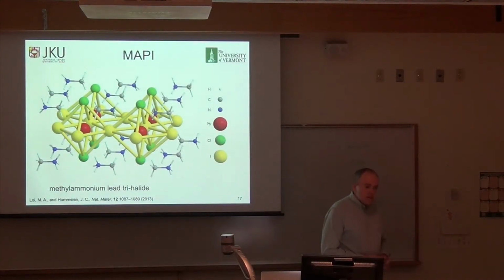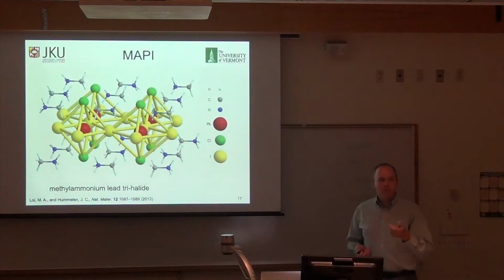To clarify what the material is — this is the material of incredible interest to everybody around the world right now. This is basically what Henry Snaith used, and the only one that works particularly well. This is MAPI, methyl ammonium lead trihalide, or triiodide. There's a lot of discussion: to make a very good film, you blend in a mixture of lead chloride and lead iodide, but nobody's been able to detect the presence of chloride in a complete film, so where this chlorine goes, nobody really knows. There's been a lot of discussion — this structure was published by M. A. Loi, a possible crystal structure, but nobody is really sure these chlorides are still there. You have a tetrahedron of lead iodide, with methyl ammonium organic molecules in between. These are little dipoles, loosely bound to the structure, but if you apply a field, they can rotate. And if you change the temperature, the structure changes, and the motion of the dipoles changes too.